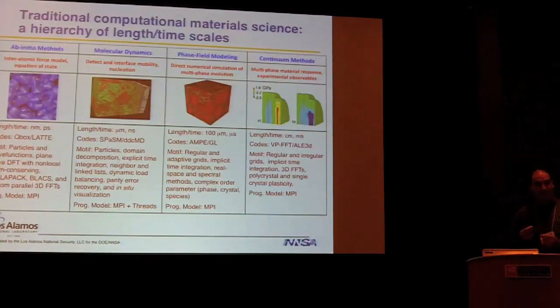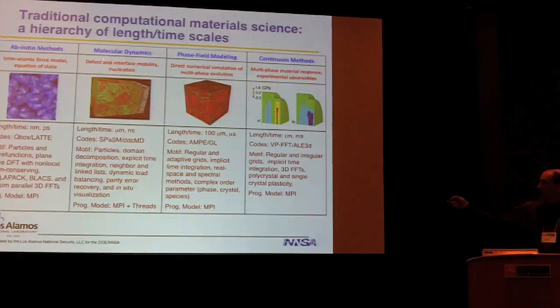So using these descriptions of the interatomic forces to model the response of materials under different loading conditions, such as a shock wave going through a material. And so this gives insight into larger length scale phenomena, how defects and new phases nucleate and grow and move around.